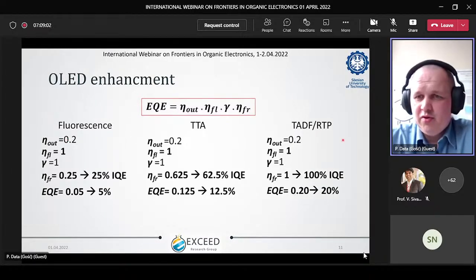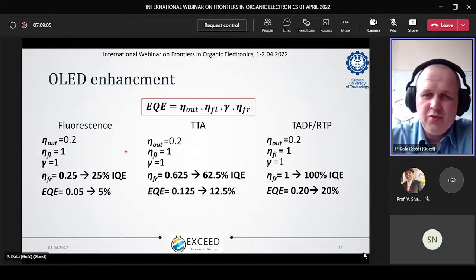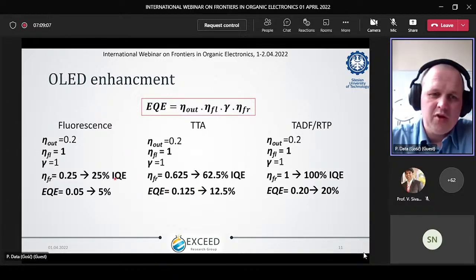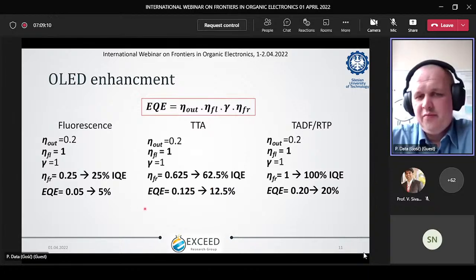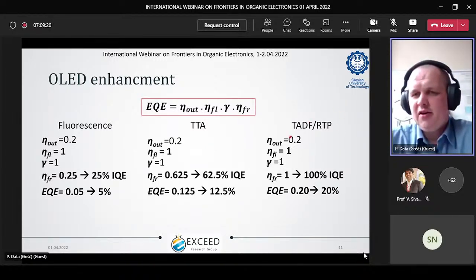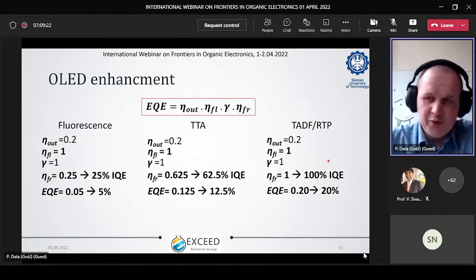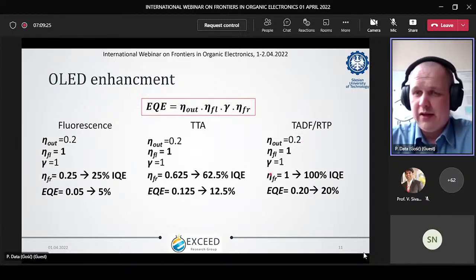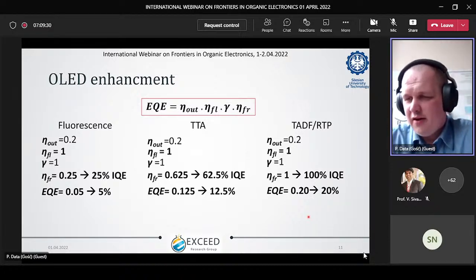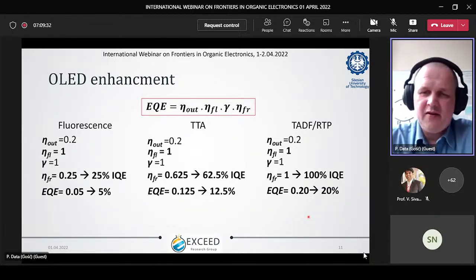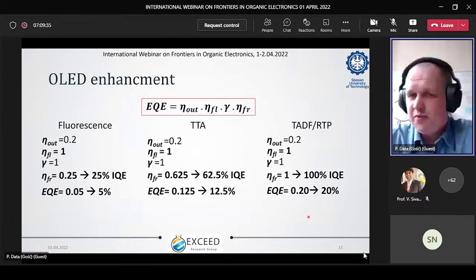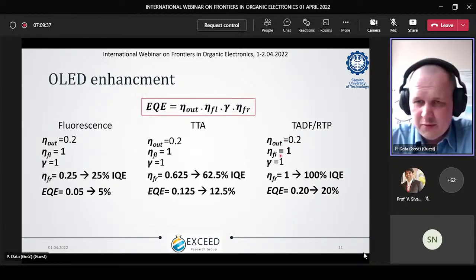That's why we assume in all of them the outcoupling is 0.2, and then depending on the mechanism, if we have fluorescence, we can get 5% of the external quantum efficiency of the OLED device. If we have only the TTA process, we can go up to 12%. And in TADF or phosphorescence or room temperature phosphorescence, which is also the case, we can go up to 20%. In the literature, you can find devices with 30% or 40%, and that's only because you are changing the outcoupling factor.